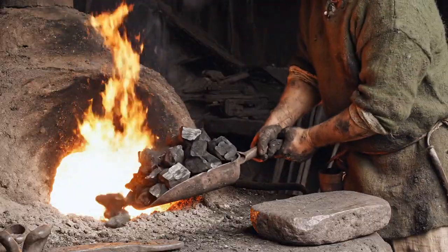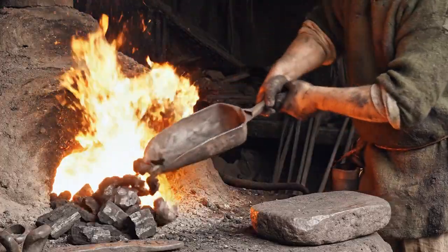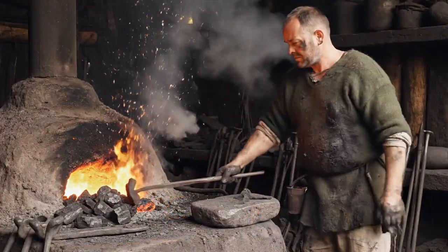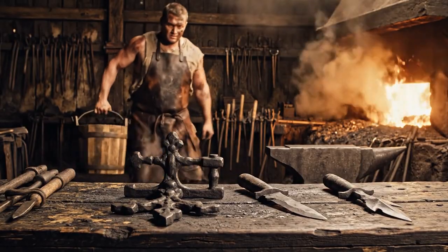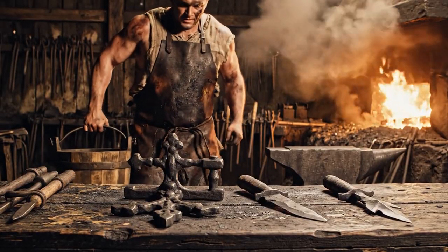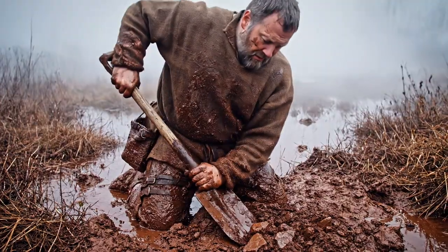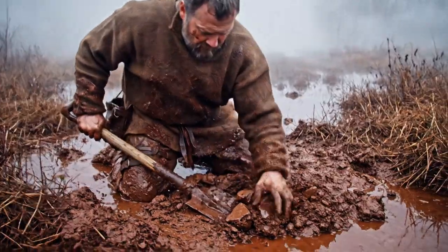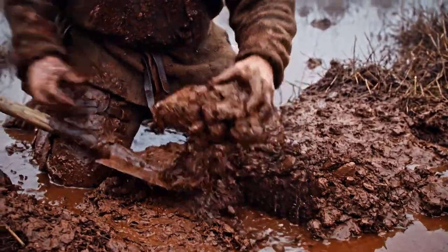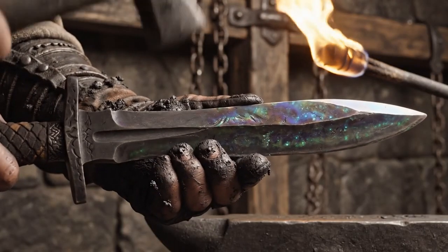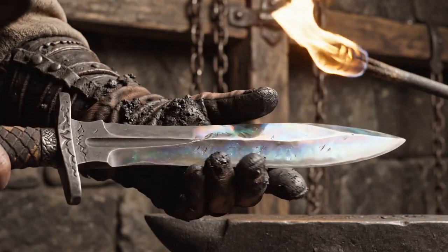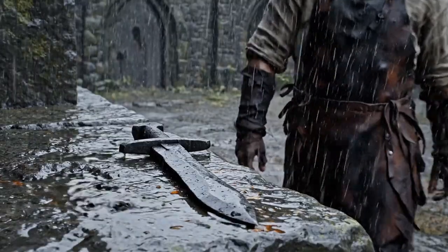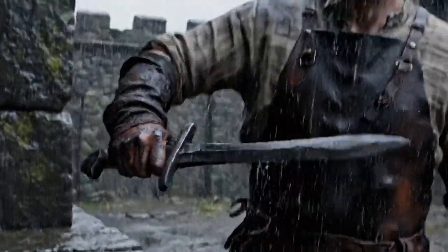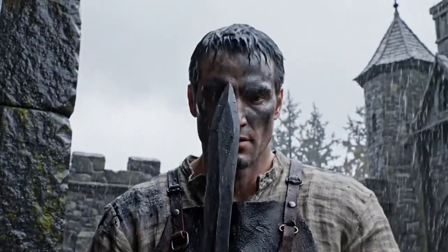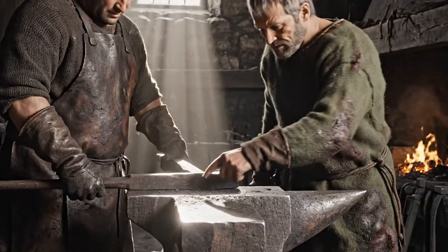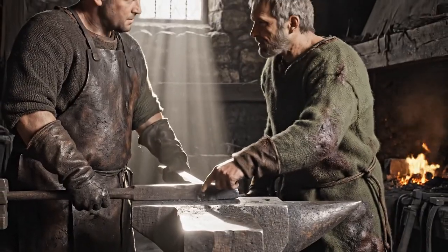Medieval knife makers exploited this by using phosphoric iron specifically for the cutting edges. Second, and more importantly for our story, phosphorus increases corrosion resistance. Iron made from bog ore, with its residual phosphorus content and often with residual silicates that form a glassy coating on the surface, resists atmospheric rust significantly better than common wrought iron or modern mild steel. This was not theoretical knowledge for medieval craftsmen. They could see it with their own eyes.